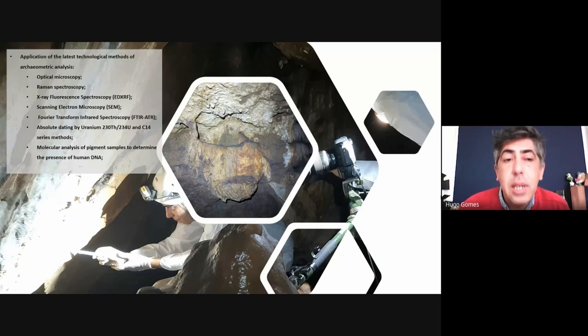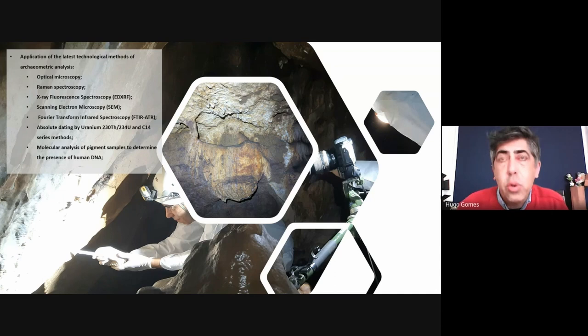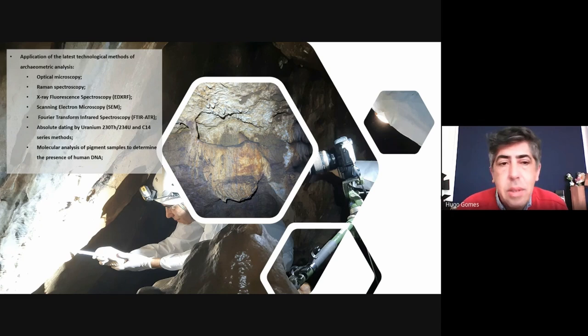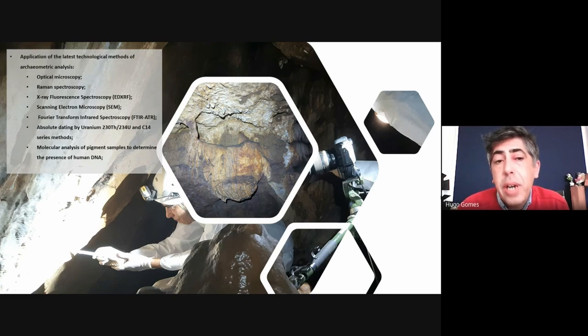FTIR gives us the possibility to identify the mineral composition but also the organic part, which is very difficult to identify. In general, the Raman and X-ray fluorescence databases don't allow us to say definitively whether something is a particular hematite or a particular specific substance. We also join to these methods absolute dating, particularly uranium-thorium dating of covering surfaces — the cover layers that cover the pigments. We started presenting results for two caves, but we now work in rock shelters and open-air sites.